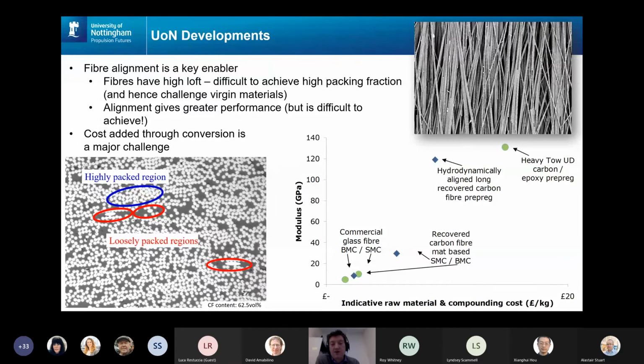material. So typically you would want about 60% fiber volume fraction. And if you just take recycled carbon fiber and squeeze it, you get about 10%. And if you squeeze it really hard, you might get 20, but then you're starting to break the fibers and reduce your mechanical properties that way. So we think that fiber alignment is a really key enabler.